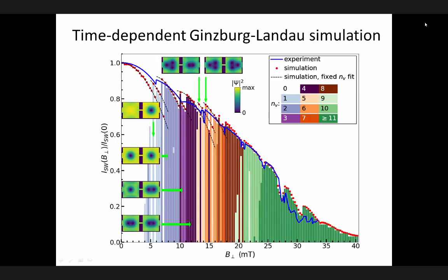So when you test the state without vortex, initially the system was found in this position, but when you try to read it out while ramping up the current, the vortex was expelled, so you see a state without vortex. So whenever this bar doesn't go all the way to the given curve, it means that the vortex was expelled on the way. This is the outcome of the simulation, okay?